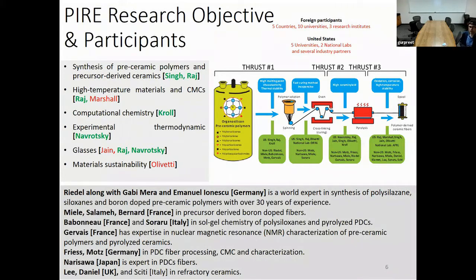And then we have research thrust area 3, which is the ceramic stage. So here we are evaluating the mechanical, chemical, thermal properties of the ceramic fiber at elevated temperatures. We are also looking into correlating the energetics of formation, transformation, and decomposition of the PDC fiber by use of high temperature calorimetry. And of course, in addition to all of this, we have a very strong computational component to it.